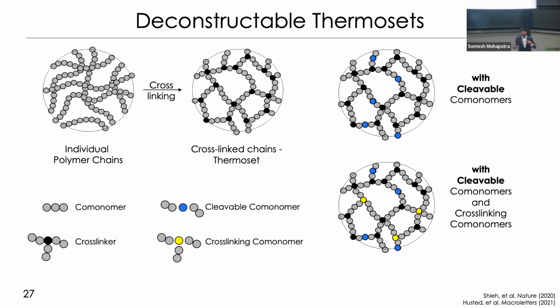Interestingly, a couple of key innovations came into place in 2020 and 2021, starting with Johnson's lab, introducing something known as cleavable comonomers. Cleavable comonomers were introduced as another set of comonomers into these chains, which ideally would not have affected the high temperature too much, but help in recyclability. And they went a step ahead and developed another class called a cross-linking comonomer, which would help in cross-linking, but could cleave them and improve recyclability further.